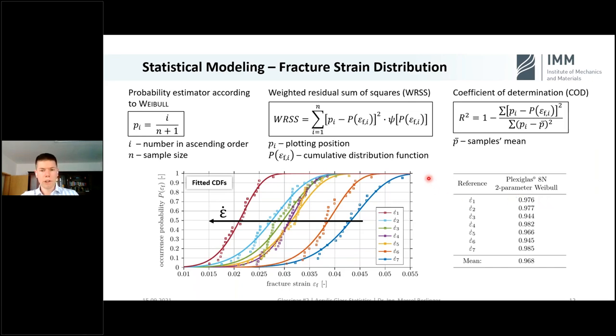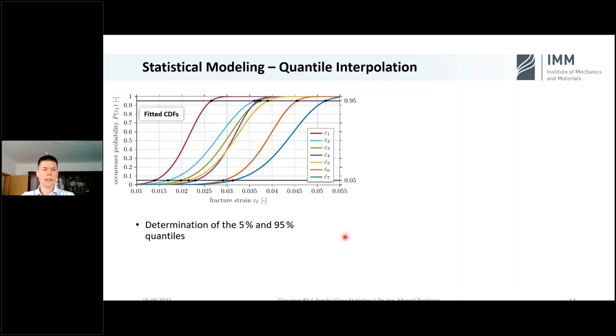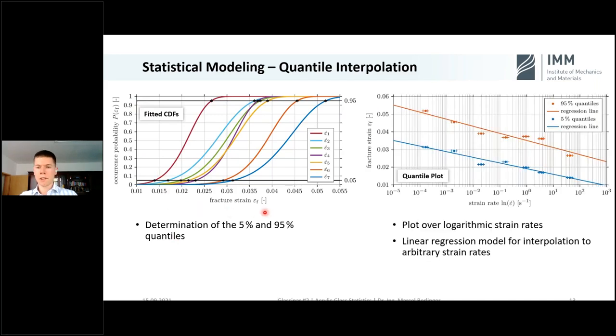Now we go further, we take the CDFs, the curves, the variable distributions, and go into a second diagram. And here we extract the 5% and the 95% quantiles. These are the stars here as cut at 5% and 95%. And when we take these quantiles and plot them over the logarithmic strain rate again, then we see that they tend into a straight line. And that was our motivation to say our model is to make a linear regression, and therefore we are able to interpolate at arbitrary strain rates.